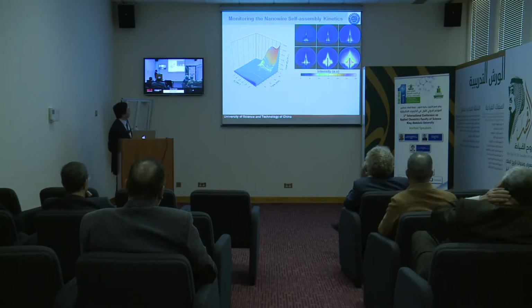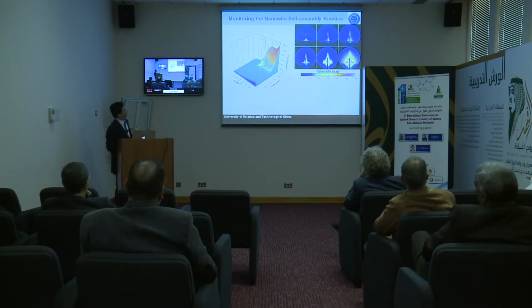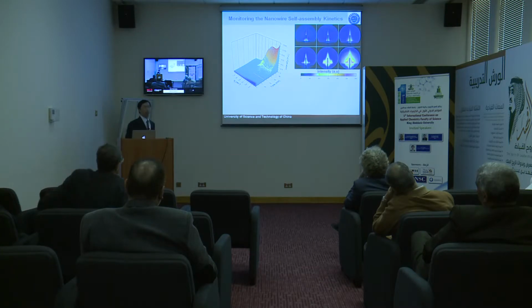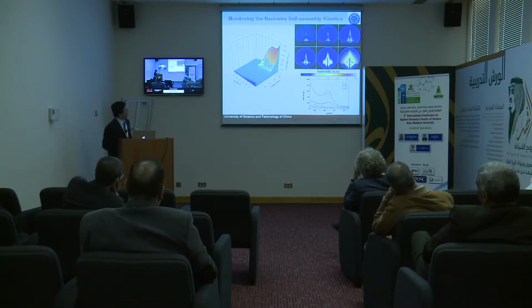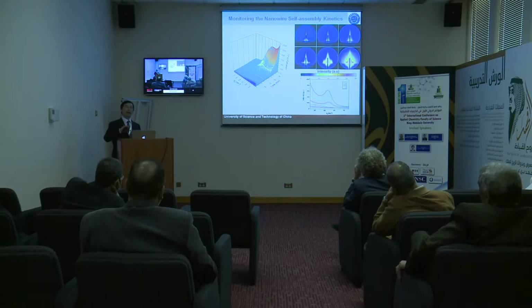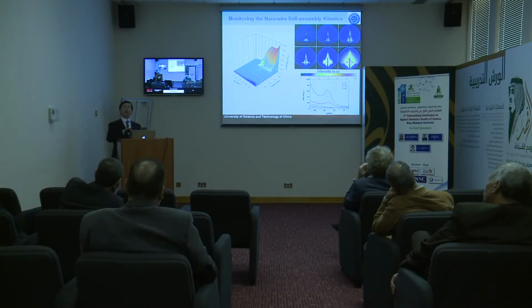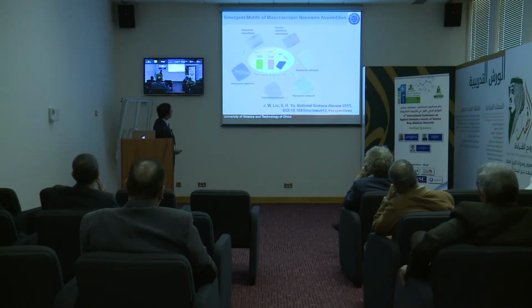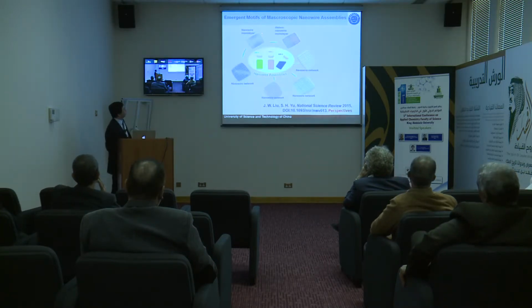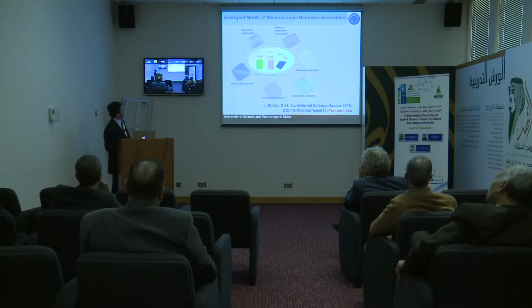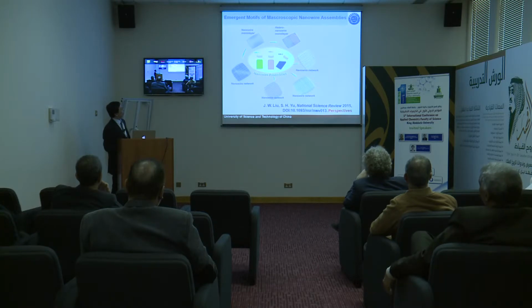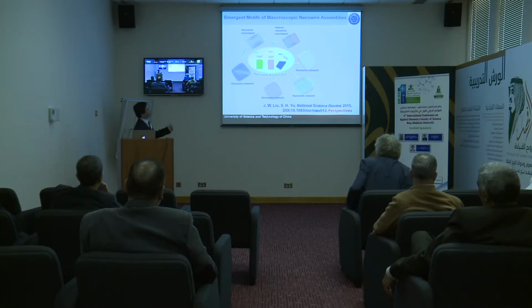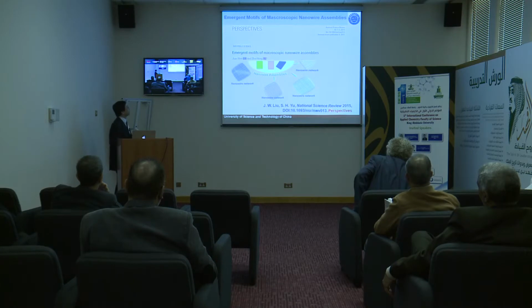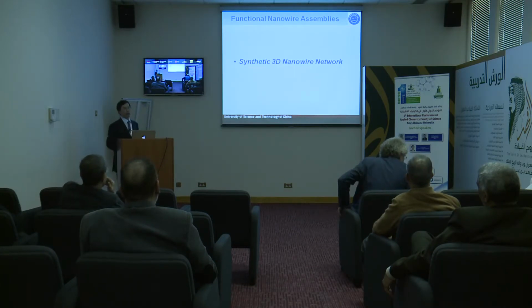So you can identify the time-dependent evolution of these nanowires during the ordering process, right? You can really identify this in the small angle X-ray, accompanying the ordered structure formation. So we propose that we can use nanowires as a building block. You can make a nanowire thin film. You can make different hybrid or hetero nanowire systems. You can further engineer them. You can do many things in the future with the nanowire assembled structure. And lastly, I talk about the three-dimensional nanowire network.